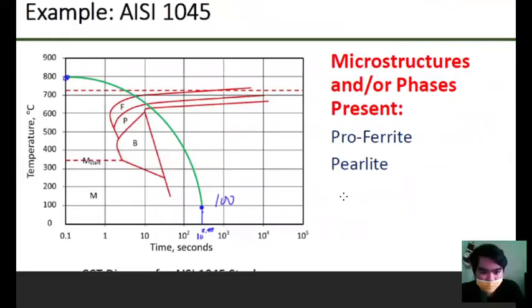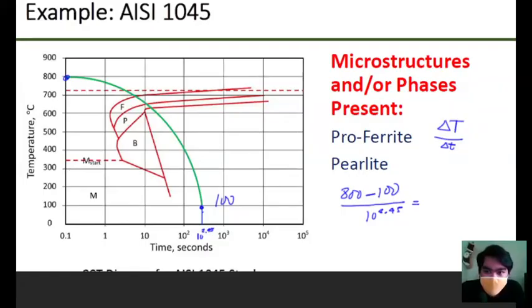So if we compute the cooling rate, we have 800 minus 100. So cooling rate is just the change in temperature over the change in time. So that's 800 minus 100 over 10 to the 2.45 seconds. So from time 0 to 10 to the 2.45 seconds. And if you compute that, that's 700 divided by 10 to the 2.45, no? Which should give me around 2.48. So ang cooling rate nito is fairly modest, no? That's 2.48 degrees Celsius per second. Okay, so that's how we can estimate, no, kung ano yung cooling rate ng isang curve.